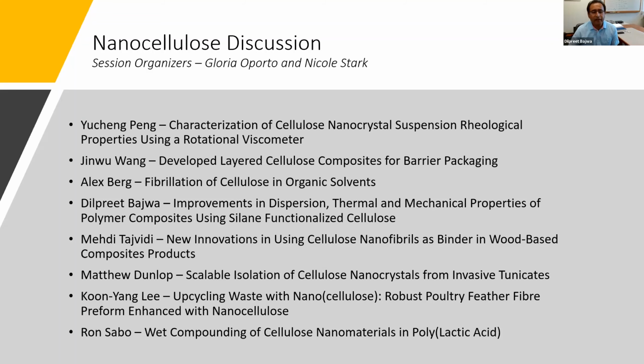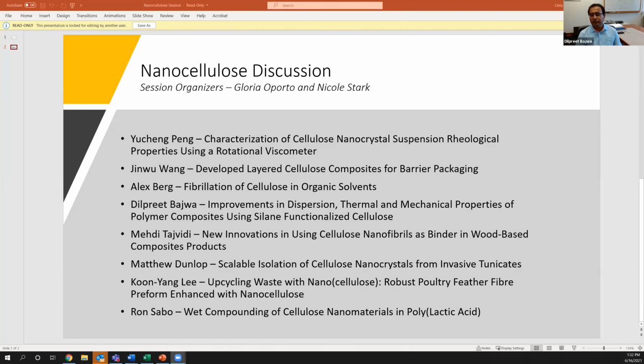So what we did in this was, first we dissolved the PEO in distilled water, DI water, and then we added CNC. That was the second step. And again, this was under constant stirring. And then we added silane, different levels of silane. And these were all done in a beaker. Once the solution was all clear, we poured the solution into Petri dishes that were Teflon coated, PTFE Petri dishes. And then we let these dry for 24 to 48 hours.